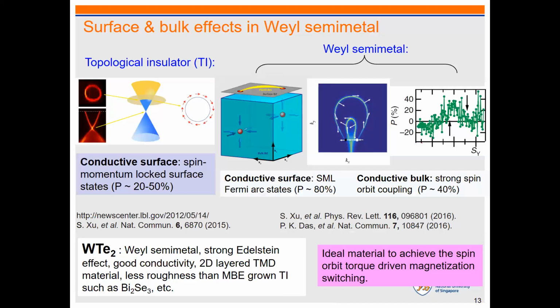So then we switched to another topological material called Weyl semimetal. This material has a more conducting bulk. You can see from the name itself, the previous one is a topological insulator, but this is a semimetal, so it's more conducting now. And it maintained quite reasonable spin polarization. At the surface state, about 80% was measured, and at the bulk, about 40%. So we saw this would be more interesting and low power.